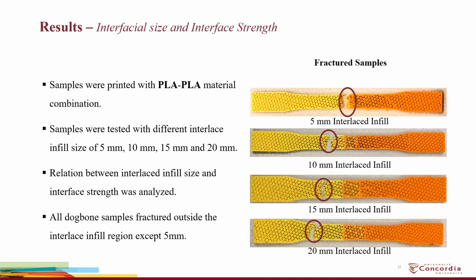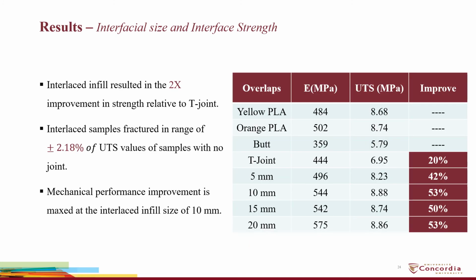To observe the relationship between interlaced infill and the mechanical strength of the samples, we performed tensile tests on dog bone samples with 5 mm, 10 mm, 15 mm, and 20 mm interlaced infill size. All the samples fractured outside the interfacial joint except samples featuring 5 mm interlaced infill, which shows that 5 mm is too small to strengthen an interfacial joint. After analyzing the different interfacial joint configurations, we observed that interlaced infill clearly outperforms the T-joint, and the improvement in mechanical performance is peaked at the interlaced infill size of 10 mm.